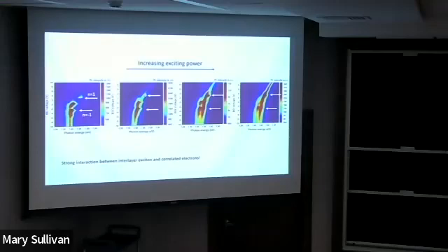We are limited by the diffraction limit. We are actually having some diffusion experiments going on. But again, the problem is the mobility of this material is not so great. The diffusion length is not so large. It's actually very close to the diffraction limit, instead of below it. Why though? I believe it's the mobility. The diffusion constant is proportional to mobility, and this material is not known to have the greatest mobility.